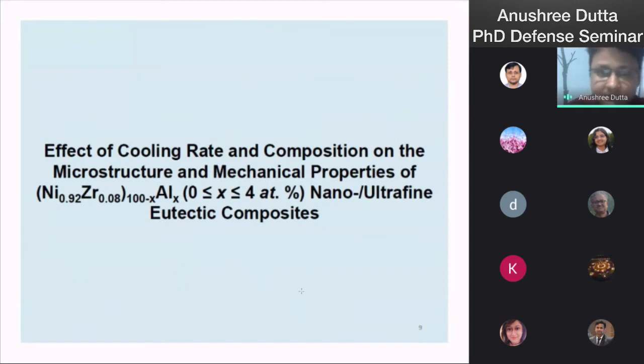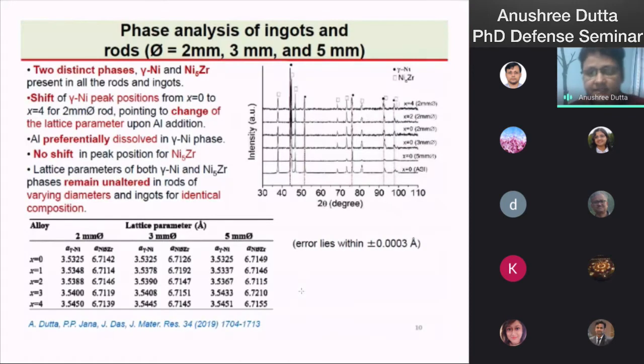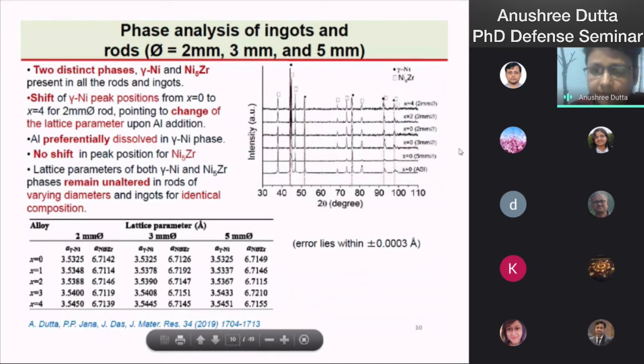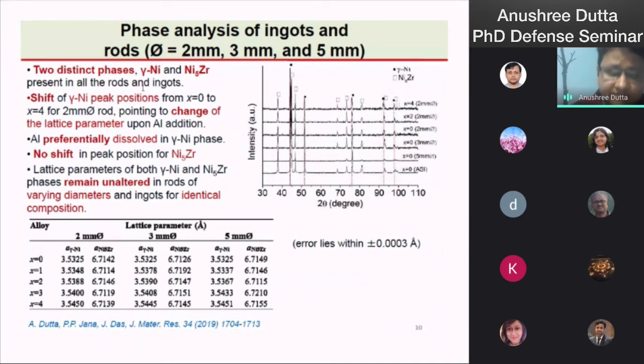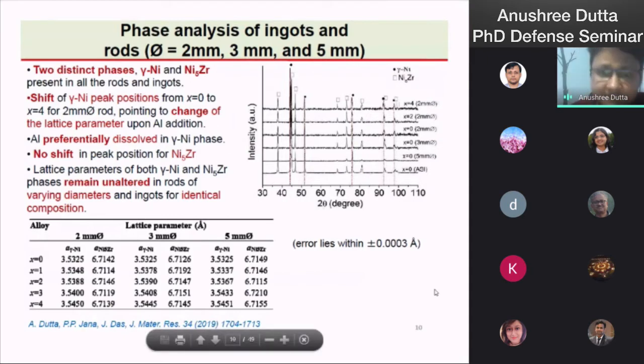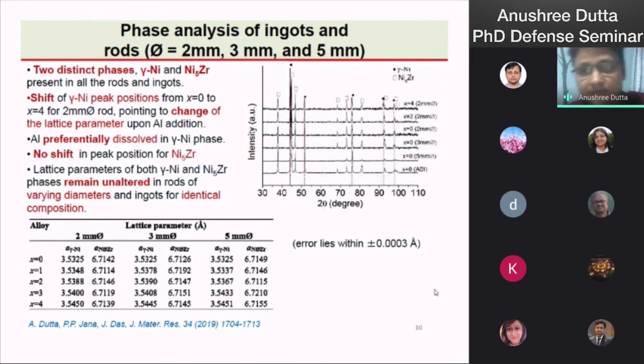The first one is the effect of cooling rate and composition on the microstructure and mechanical properties of these alloys. The X-ray diffraction pattern at room temperature shows that two distinct phases are present in the alloys, gamma nickel and Ni5Zr zeta. The X-ray diffraction peaks of the gamma nickel phase are shifted towards lower 2 theta values, which shows the change of lattice parameter